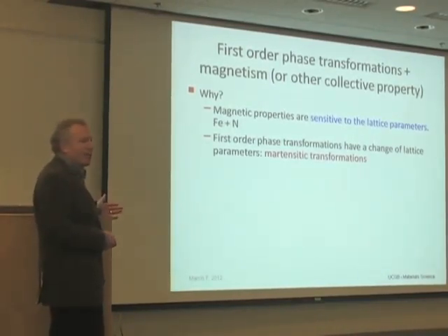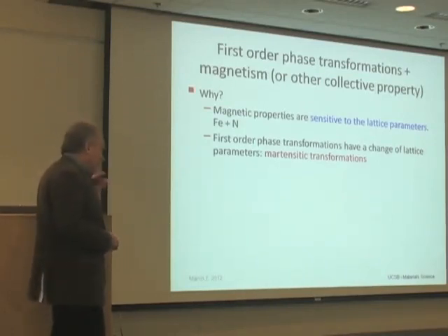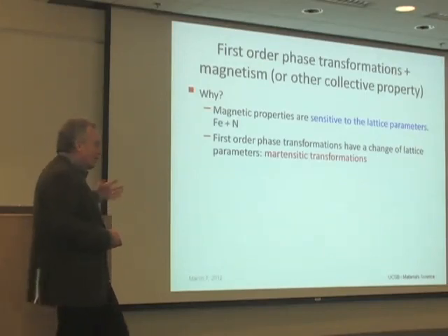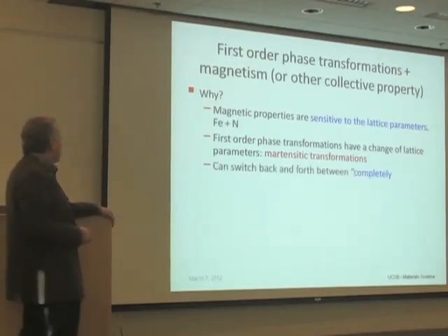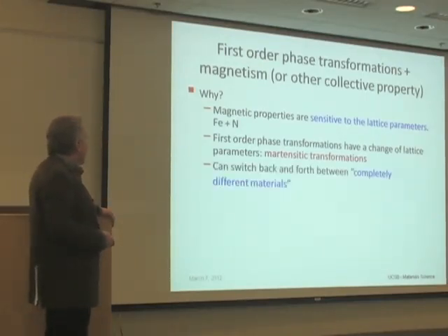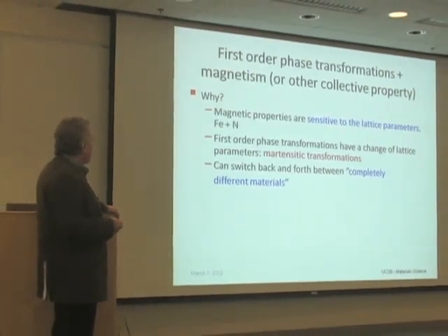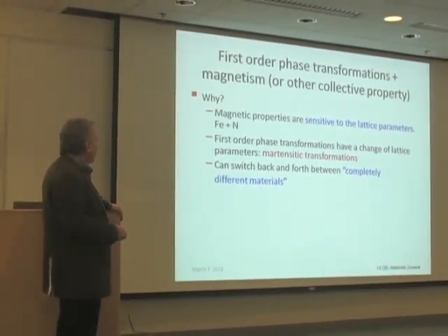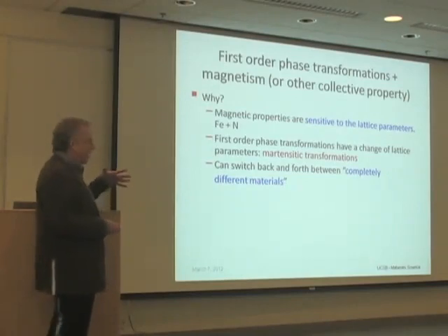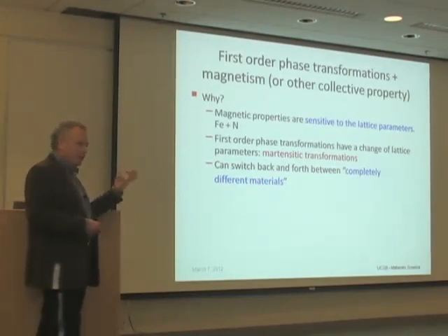I'll look at transformations with a real transformation strain, maybe like 10% transformation strain, big first-order phase transformations. And therefore, since they have a change of lattice parameters and magnetic properties are sensitive to the lattice parameters, you can think about, if you design the material property, switching back and forth between completely different materials magnetically.